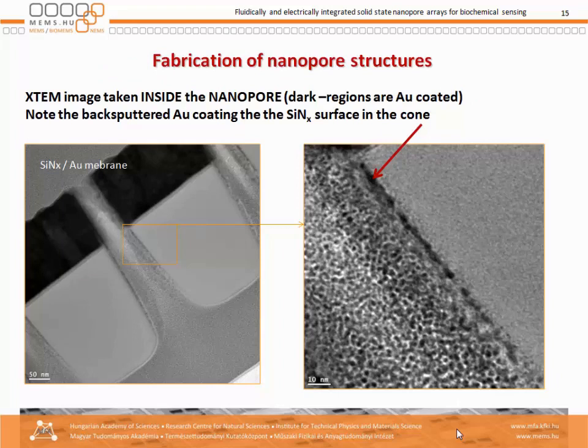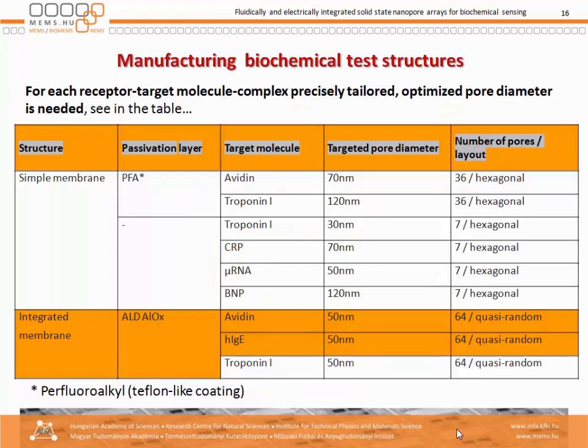We have gold on top of the membrane, and this gold layer gives the entrance or output opening — the gold layer appears dark in this cross-sectional picture. However, during sputtering by gallium or argon ions, we also coat the internal surface of the non-gold materials, shown as a black line here, which can be beneficial for functionalization.